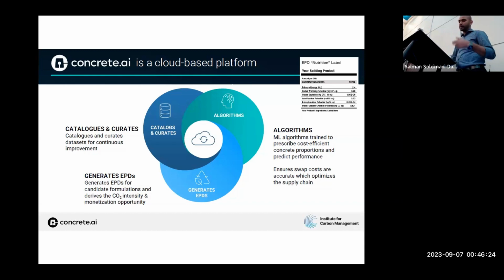And we spent a lot of time looking at this, did a lot of work on trying to see if we could use an algorithm, classic data science, right? Machine learning, to actually analyze these data sets, understand what the influential indicators were, and optimize. In effect, the optimization opportunity around cement turns out to be somewhere between 5 to 15% reduction. Obviously, it has implications on cost. Depending upon the SCM palette that you have access to, you can reduce effective carbon emissions in the binder, as an example, by somewhere between, give or take, let's say 10 to 30%.